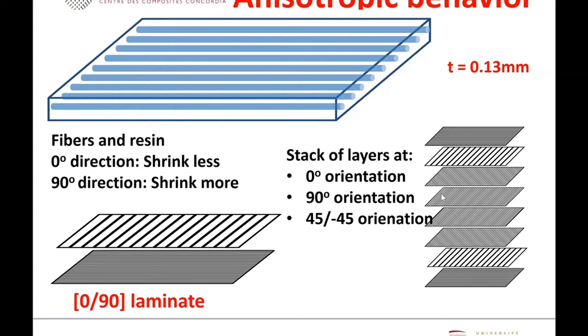Except that usually in an airplane, they look only at symmetric laminates, I mean laminates that do not bend or curve. In our particular case, we are looking into the deformation. So take a look at one simple case, such as a laminate here that consists of 0-90. That means you have a laminate consisting of 2 layers. One layer below with 0 degree orientation, where you can see the fiber running along this direction, and one layer above that along the 90 degree orientation. We call it a laminate, a combination of 2 of these layers together.